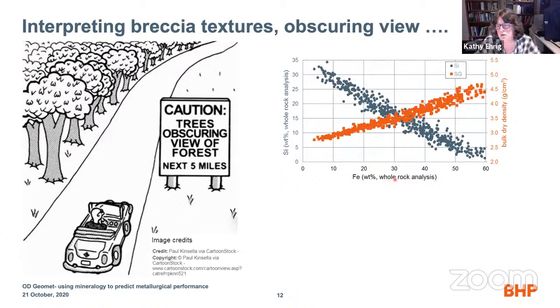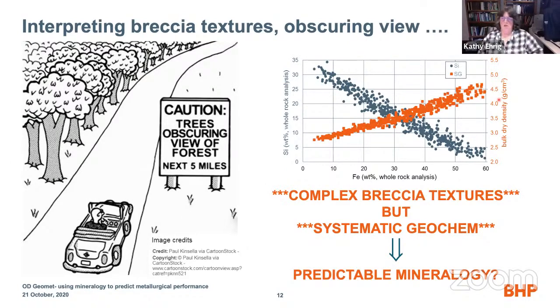But what's also shown in here is simple things like the iron versus the bulk dry density, of which we do measurements. And that's what that actually shows. So it says that as iron increases, the bulk dry density increases, and this also helps to explain some of our geophysical anomalies.